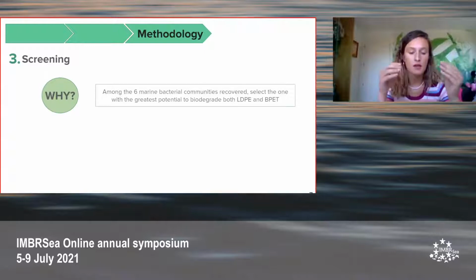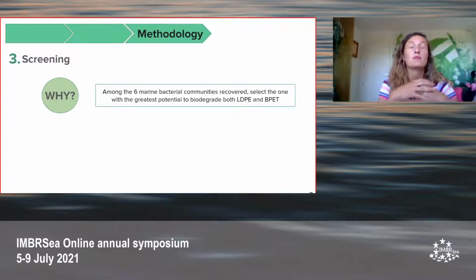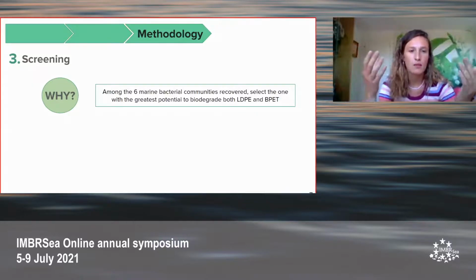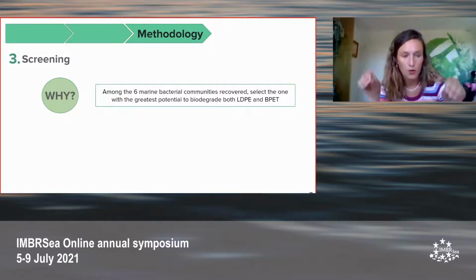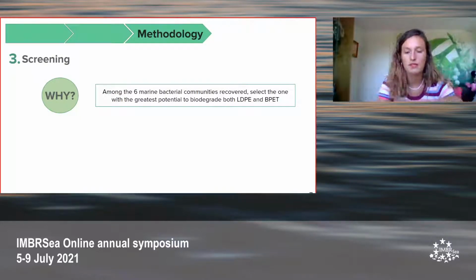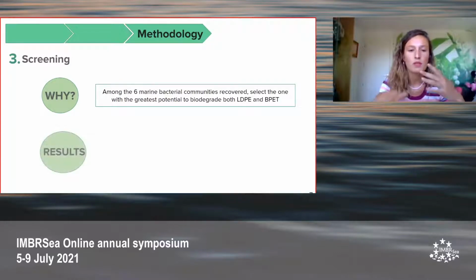Okay, so previous to our biodegradation experiment, we performed a screening. Why did we do this? Since we didn't have the time to carry out the experiment for the 6 marine bacterial communities recovered, we had to select the one with the greatest potential to degrade both polymers, and this is why we did this test.